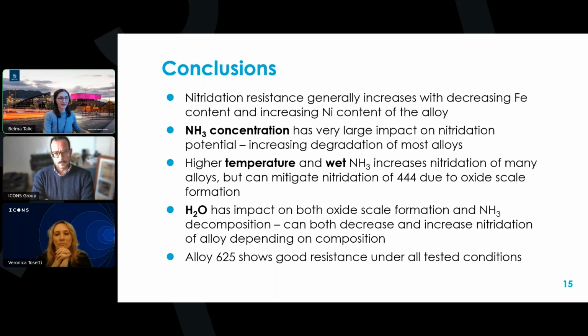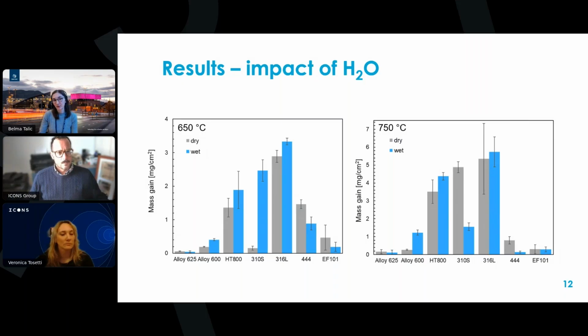Thank you. Yeah, thanks a lot for those questions. Regarding the chromium evaporation, I don't believe that it's impacting our mass gain results that much. We should remember that although we're adding 2% of steam, the atmosphere otherwise is quite reducing because we have such a high concentration of ammonia. And in order to have significant evaporation of chromium, we would need to have a higher partial pressure of oxygen as well, I would think. I haven't seen any measurements of evaporation in these conditions, but at least in hydrogen mixtures, the evaporation of chromium is greatly reduced compared to oxidizing wet conditions. But of course, we cannot rule out that it's influencing it to a small degree.